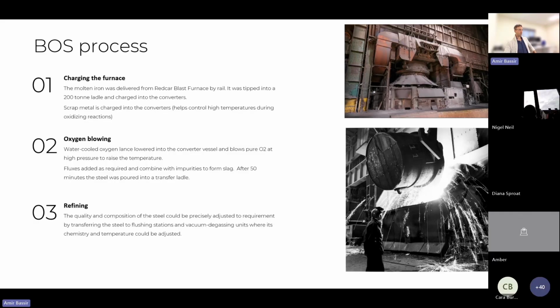The first stage really is charging. The molten iron is delivered by rail and tipped into a 200-ton ladle and carried to converter vessels, such as that one there. The BOS plant had three 250-ton capacity converter vessels. These are tilted forwards and charged with scrap metal, which helps to control the temperature during oxidizing reactions. An overhead crane carries the ladle in, and the molten iron is poured into the converter, which is then returned back up to upright position.